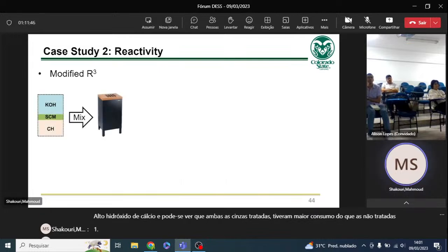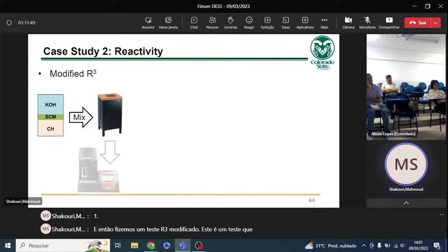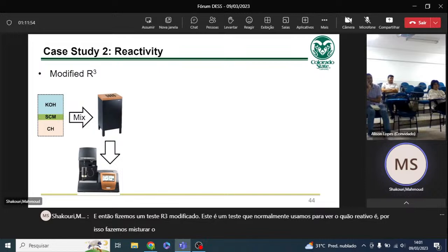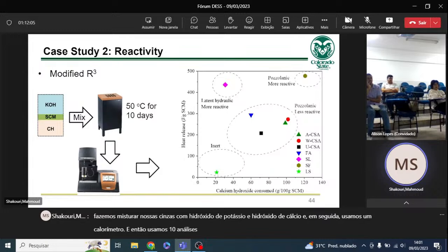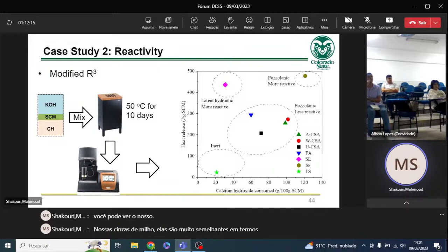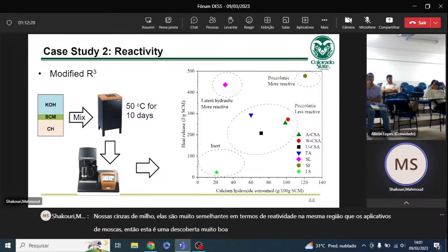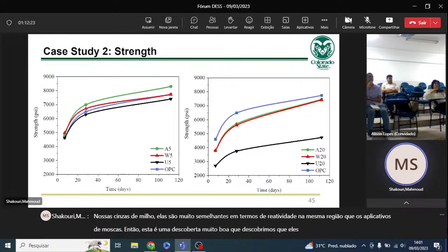And then we did a modified R3 test. This is a test we typically use to see how reactive it is. So we mix our ash with potassium hydroxide and calcium hydroxide, and then we use a calorimeter and thermal analysis to determine how much calcium hydroxide is consumed. And as you can see, our corn ashes are very similar in terms of reactivity, in the same region as fly ash. So this is a very good finding, that these ashes can be a really good